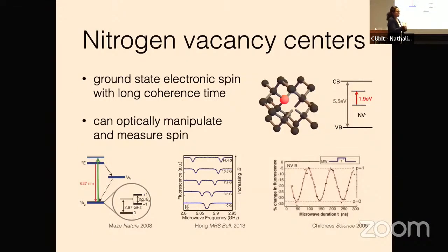And the coherence time is just limited by the number of nuclear spins in your vicinity. And fortunately, carbon is mostly carbon-12, so you don't have that many nuclear spins. And you can do things like isotopically purify the environment to get really, really long spin coherence time. So people sort of routinely work in the many milliseconds range, even at room temperature. So that's what makes this very special.